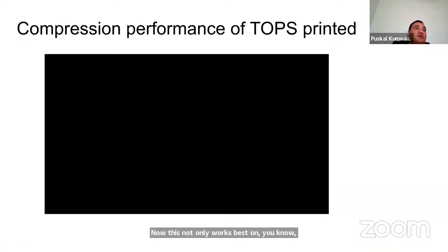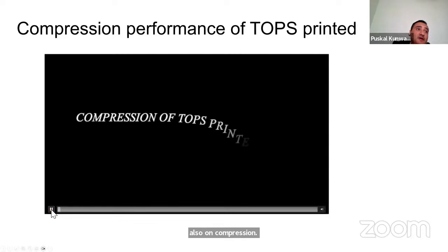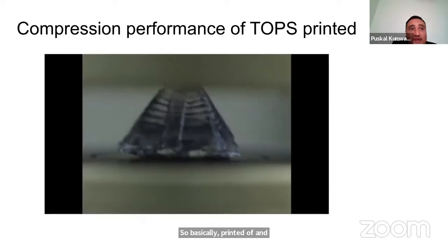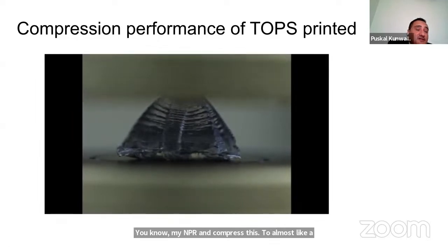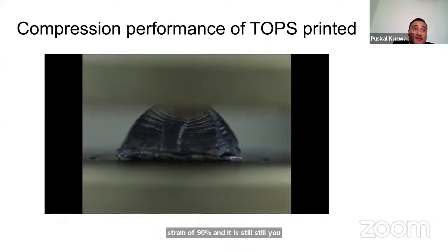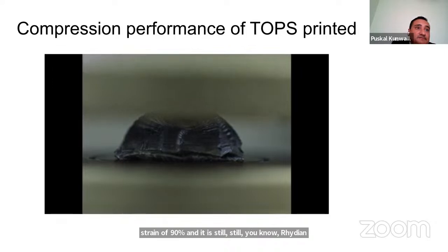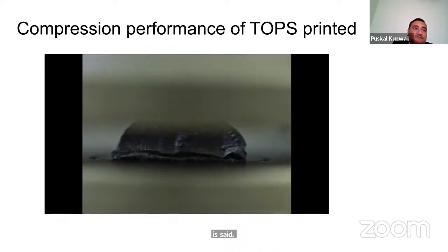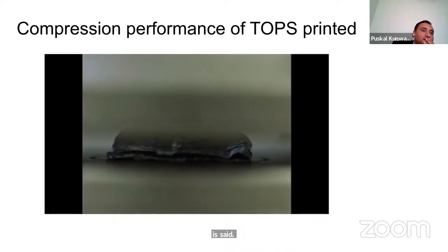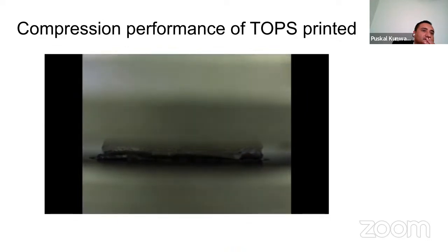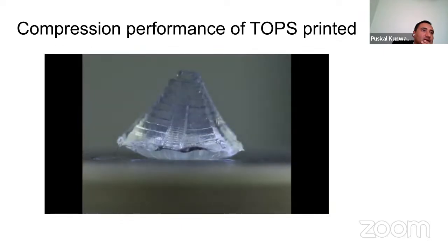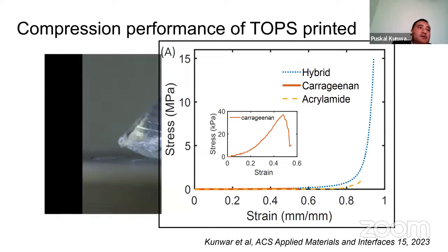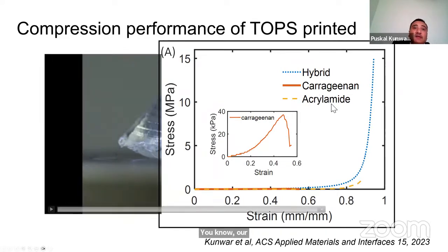Now this works not only on tension, but also on compression. So we printed a Mayan pyramid and compressed it to almost a strain of 90%, and it still regains its shape. Our compression stress strain test says that our hybrid gel is better than its parent gels, carrageenan and acrylamide. You need almost 15 MPa to crush the structure to pieces.